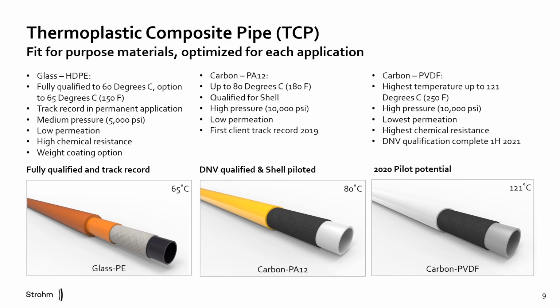With all of the benefits of polyethylene for mid-level applications, this is the workhorse of the TCP product line. For more specialized or onerous applications, we have 2 material options utilizing carbon fibers for reinforcement. These are intended for high pressure and deep water, but also extend our operating temperature window up to 80 degrees C for nylon and 120 degrees C for PVDF.